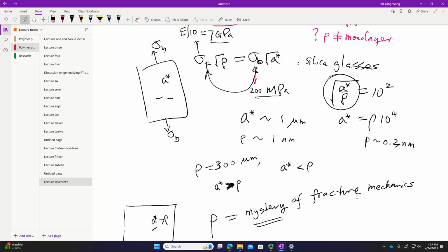I keep reminding you, right? So now you start to connect that if rho is 300 microns, then I can already conclude your measurement is free of any influence of flaws, because I don't see flaws. Or flaws need to be of size larger than 300 microns to weaken my material, which I don't see. So therefore, I conclude my sample is not a fracture mechanical phenomenon when I break it. When I break it, I essentially see my material reach the inherent strength somewhere, not around some flaws.